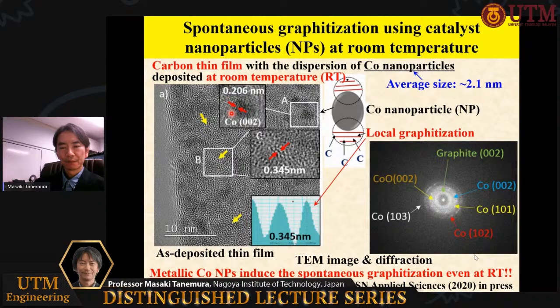At around and in between cobalt nanoparticles, short-range fringes are observable. Their spacing is about 0.345 nanometer, which corresponds to the graphite 002 plane. So, the very localized graphitization occurs even for the as-deposited film at room temperature. In the electron diffraction pattern, we observe graphite 002 ring and several spots from cobalt and cobalt oxide.